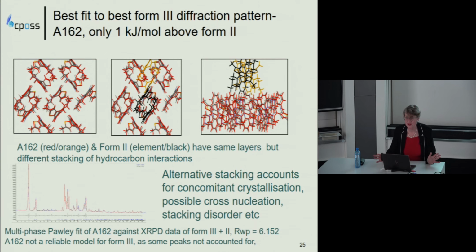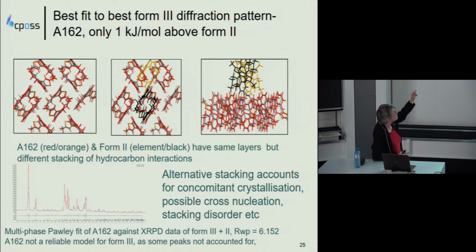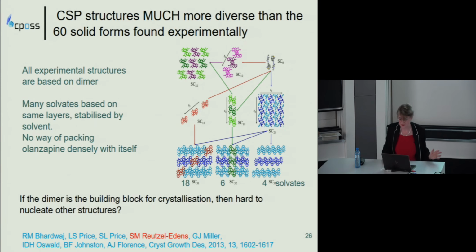So to try and find form 3, you look at the powder patterns from all the predicted structures and could find one which was only a kilojoule per mole above form 2 that looked very plausible. You can see in this overlay, essentially the same layer structure, but the layers are stacked in a different way, and it's only how the hydrocarbons are dealing with weak van der Waals forces. The two being related by alternate stacking accounts for the concomitant crystallization, maybe cross-nucleation, or is it stacking disorder, but just the complexity of the problems they're having with it. And so, although it's not an absolute kosher model, it looks like a very good explanation for this.